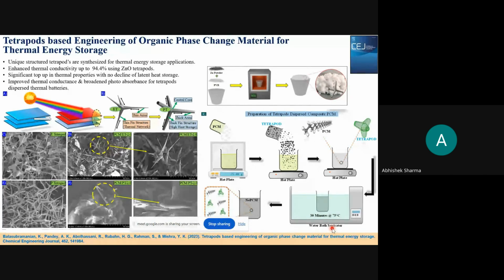And what we have done, we have used these unique structured tetrapods. We synthesized and we enhanced. We found that thermal conductivity was enhanced up to 94 or 95% using the tetrapods, and there was a significant top up in thermal properties with no decline of latent heat storage. That is one of the important parameters, that you are enhancing the conductivity without compromising the latent heat storage.